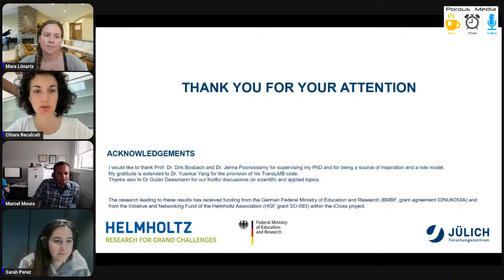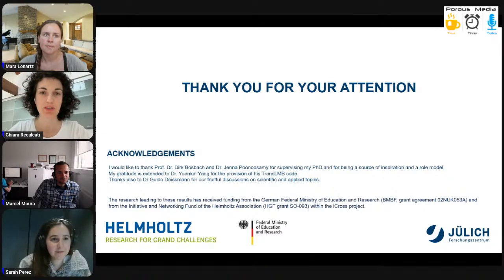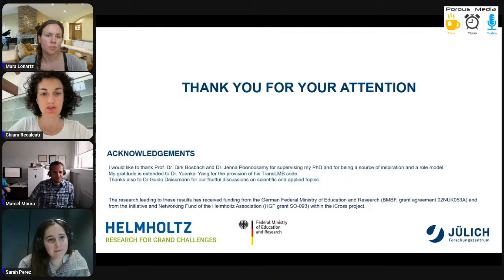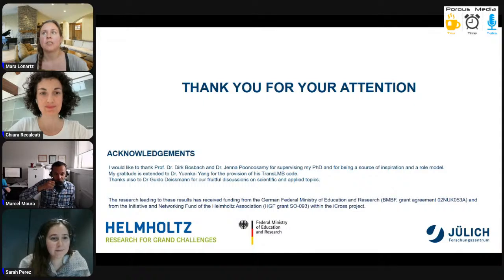I have just a curiosity. In your first project, did you also try it with some heterogeneous geometries of the microfluidics, or just with these homogeneous distributions of the pillars? Just with this one. That was also the idea, but I also tried this with the second setup, but it was taking too much time because the second chip was pretty big, and just from the modeling I could calculate that it needs 14 days to expect precipitation because it takes so long to diffuse from one end to the other end.